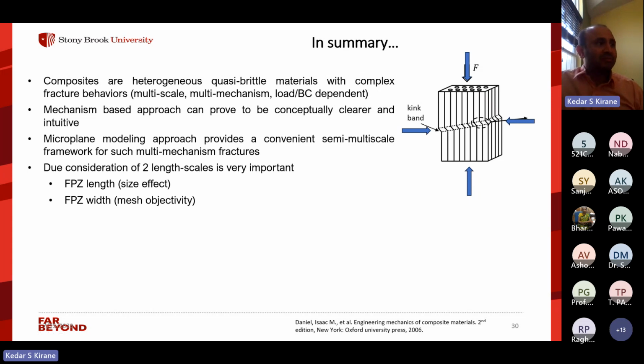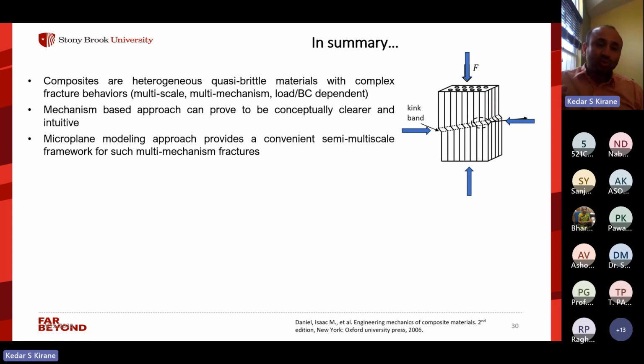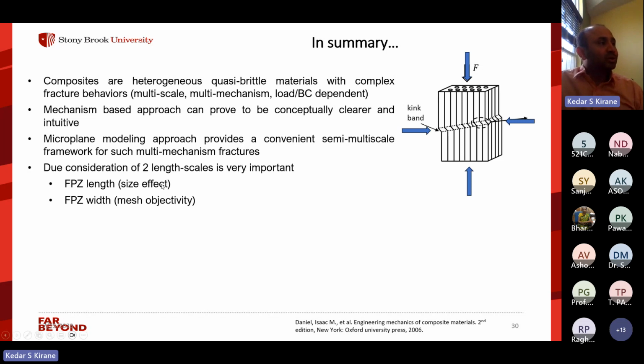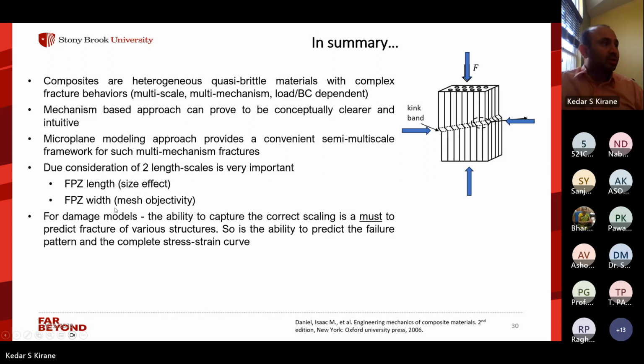It's a semi-multi-scale framework, which allows considering two length scales, the lower length scale and the macro length scale. And another point to note is that we have to distinguish between the FPZ length, which is related to the fracture energy in the model, and the strength. There is also the FPZ width, which is necessary in models to achieve mesh objectivity. And so both of these lengths have to be accounted for in the model.